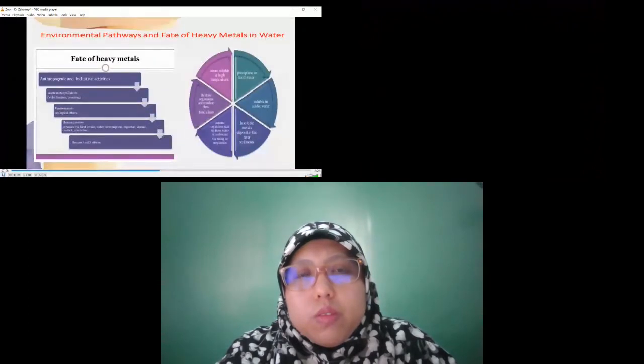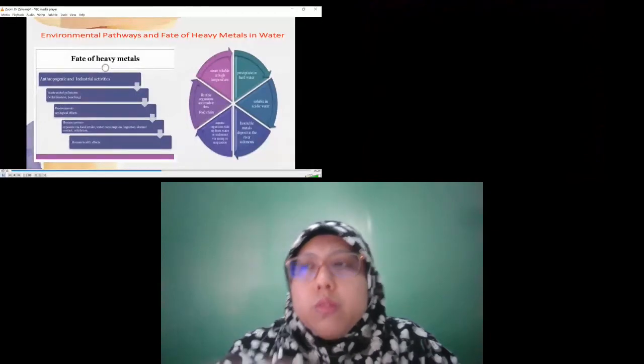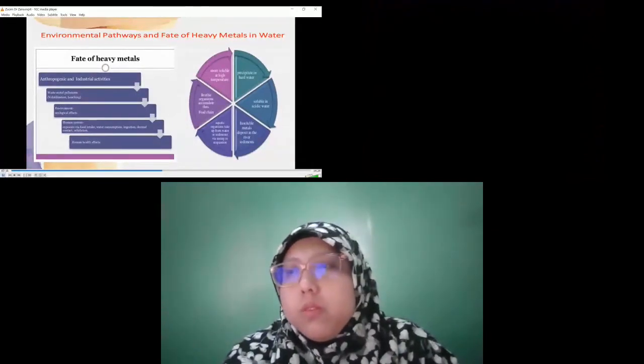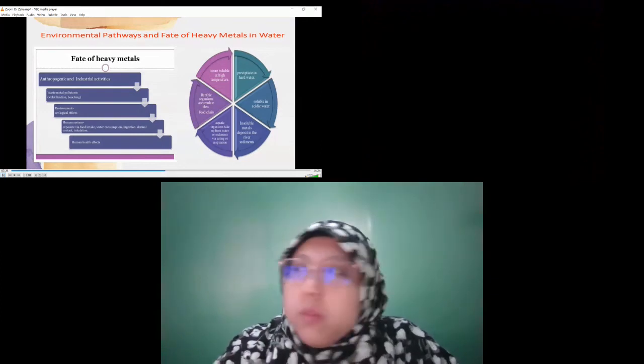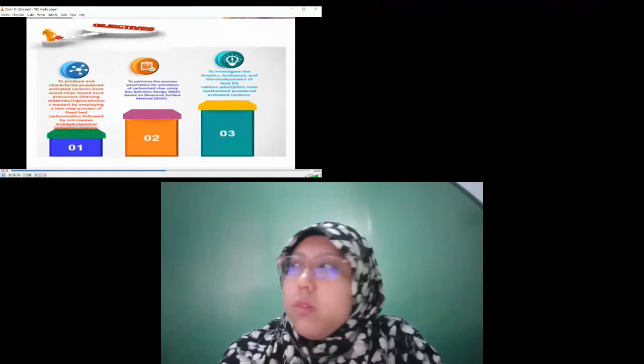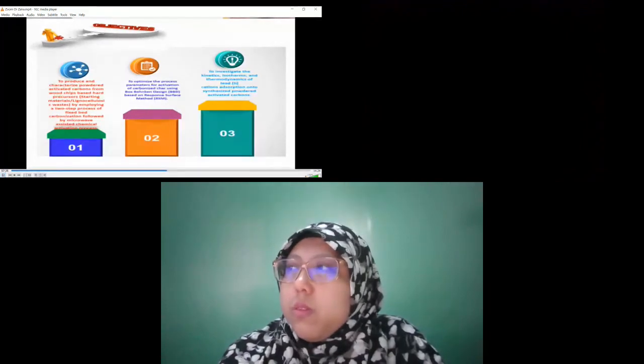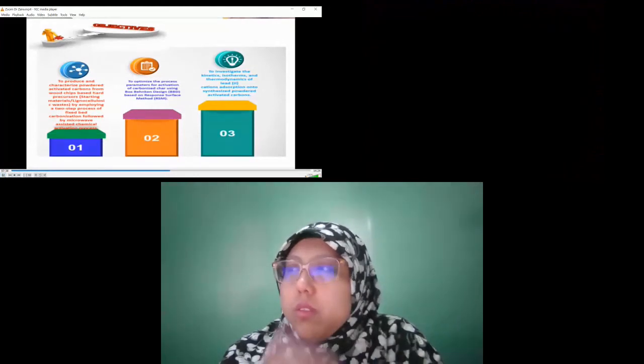If we consider the environmental pathways and fate of heavy metal in water, we can see that these are very persistent, and they have bioaccumulating tendencies. From soil sediment, they can go to the highest member of the food chain, that is, to us. So our objective is to prepare activated carbon by a two-step method, optimize the process parameters, and see the effect of activated carbon on lead cation removal. Of course, for the adsorption process, we will determine the kinetics and isotherm parameters.